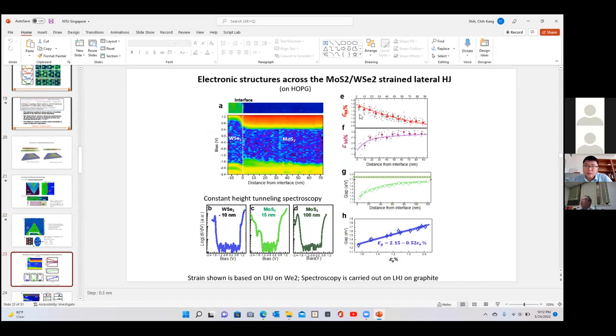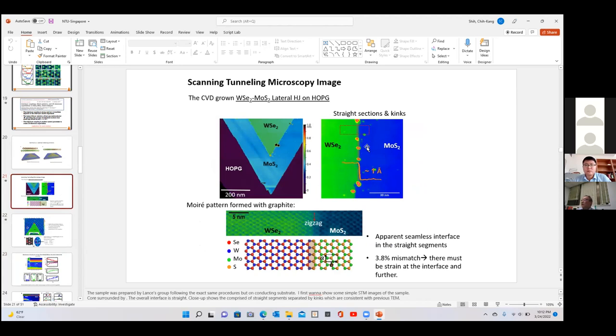Remember, when we use the moiré, our spatial resolution is about 5 nanometer, because we are limited by our moiré periodicity. So by the time we get close to the interface, if you track that, you only have a strain of about 2%. What happened to the other 2%? Well, the other 2% is really relaxed, because here you have misfit dislocations, and that misfit dislocation relaxes the strain. So right here, this part will be about 4% strain.